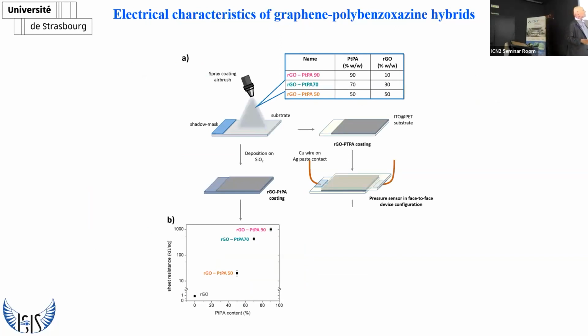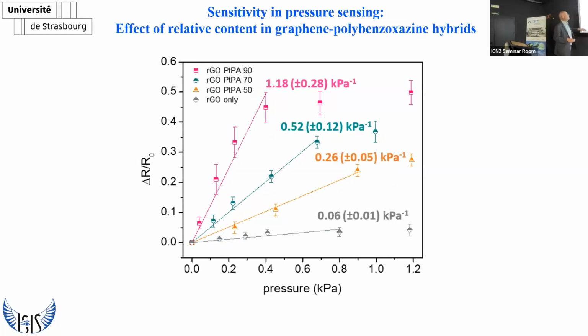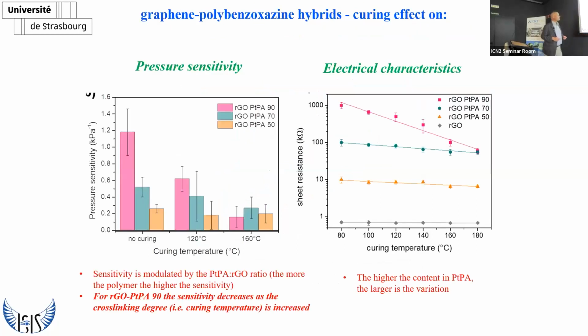We can also modulate the mechanical properties by deciding how much RGO we use and how much polymer base we use. Of course, we change the resistance, but we also change mechanical properties, because RGO is the one that brings electrical conductivity, and the polymer is insulating. And so we fabricate the very same device, a pressure sensor. And so you can see that when we use more soft material, so more polymer, we have a higher sensitivity, and lower sensitivity is when we use more RGO. I will not go into the detail, but of course you can tune the sensitivity by the composition, RGO versus polymer, and by the temperature of the curing.